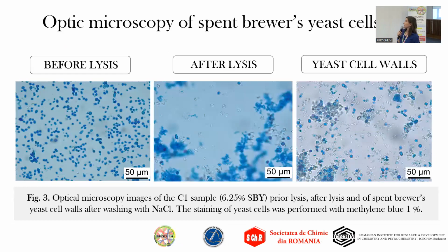Optic microscopy was used to analyze the spent brewer's yeast cell lysis. An optimal sample was assessed. The yeast cells were stained using methylene blue. In the first image, the unprocessed intact cells can be observed, in contrast with the second image, which shows the lysed cells. The intracellular content is released. It forms aggregates. It still retains the methylene blue stain.